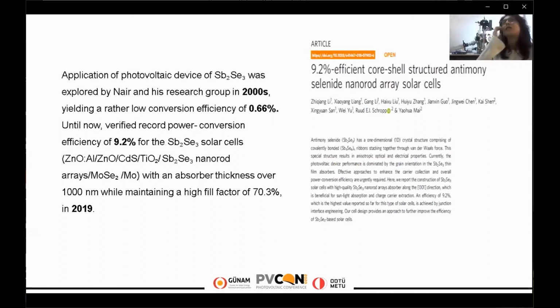And actually, if we look a little at the history of antimony selenide material, it was first explored by Nair and his research group in the beginning of the 2000s as an application for photovoltaic devices. But of course, yielding a rather low conversion efficiency of 0.66%. And until now, so we can say for 20 years, studies have gone on with antimony selenide, and the verified record power conversion efficiency of 9.2% for antimony selenide solar cells was reached by Lee and his research group in 2019.